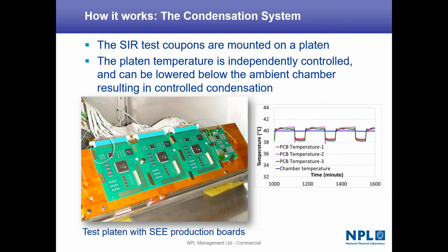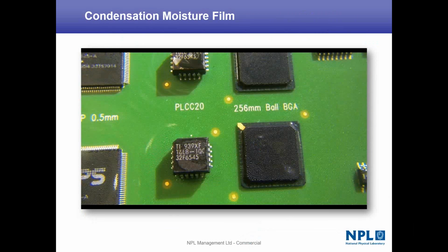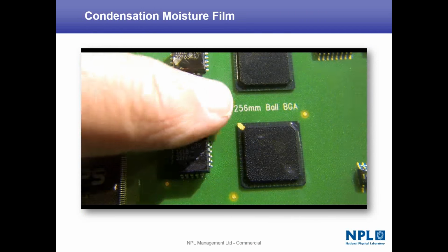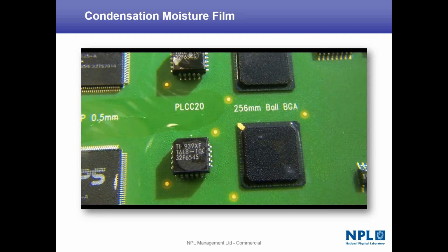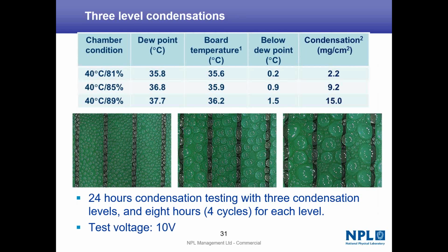The new method we used for the testing, which will be covered and talked about in the papers that Martin will be presenting in the workshop, is condensation testing. And basically what we're able to now do is do condensation testing on boards, and you can see 3 of my boards in the test chamber, and we can control the amount of moisture which is condensing on a surface. So effectively, if you look at a board that we've taken out of a chamber, and this is a very basic example video clip where you can see me literally just wiping the moisture off of the surface of the board and components.